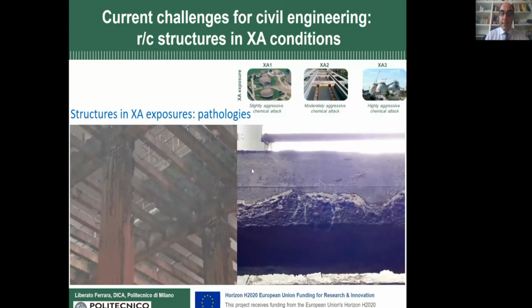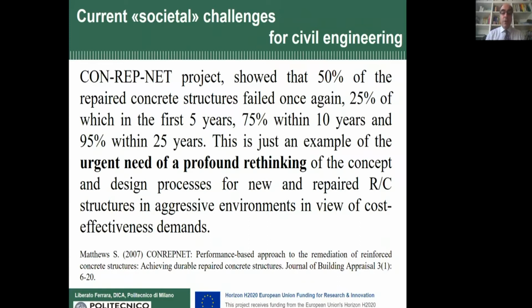So as a matter of fact, we also have to think of the durability of our retrofitting, because recent studies have shown that 50% of repaired concrete structures fail once again, and 1 over 4 among them in just 5 years after the repairing. So as a matter of fact, we have to look into a different performance than the strength,